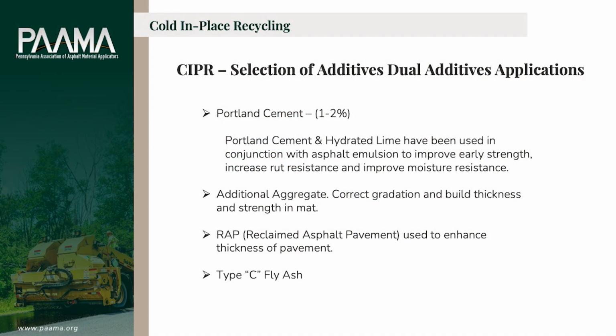So we use a dual additive. We're using Portland cement in a lot of our mixes. We're starting to educate people, townships, and they're starting to use this. It's about a 1%. So 1% is about 5 pounds per square yard. That is placed on the asphalt ahead of the recycling train. The recycling train will pick up that Portland cement along with the desired depth that we're recycling. They're all mixed together with emulsified asphalt in the cutting mandrel, placed directly into the paver and struck off.